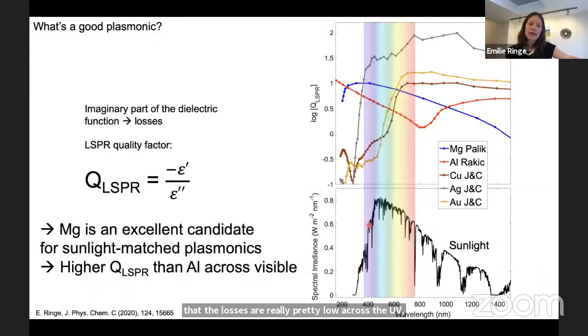Another way to express that is the quality factor, which is basically a ratio of the real to imaginary part—the bigger that ratio, the better. I have this plot of that ratio, and on top I've put a little rainbow to show the visible range, and I've also dropped the sunlight spectrum at the bottom. My conclusion is that apart from silver, magnesium is really pretty good for sunlight-matched plasmonics, and we should really consider it a real contender for whatever application we intend to do with plasmonics.